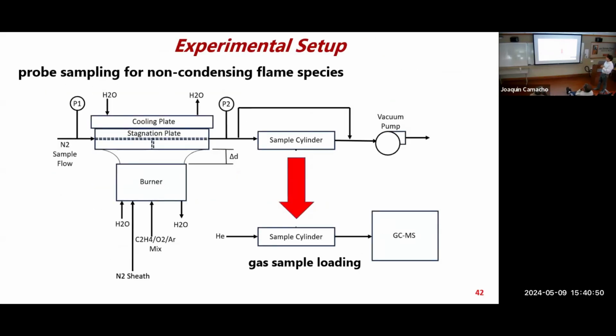So what we do is this PAH, there are some challenges that go into taking these measurements, because the precursors we're interested in are gas phase in the flame. But as soon as you take them out of the flame to normal temperatures, the heavy precursors condense. The big molecules that were gas phase in the flame, they condense. That can cause problems because a measurement that would work for smaller gas species like CO2, hydrogen, and water, it'll work fine just by simply directly feeding a line into an analyzer.